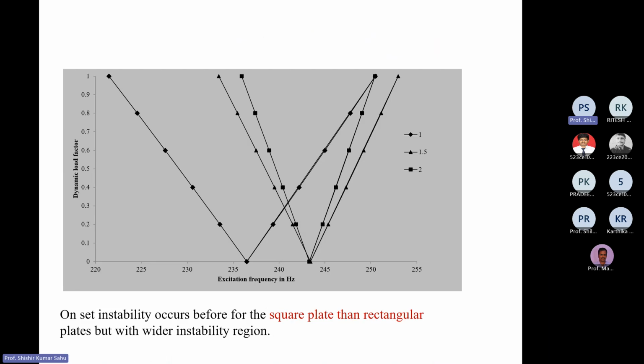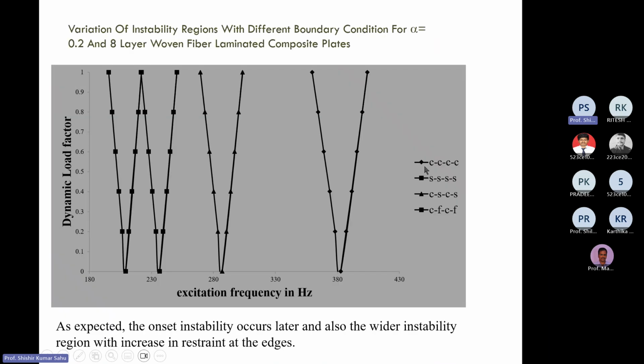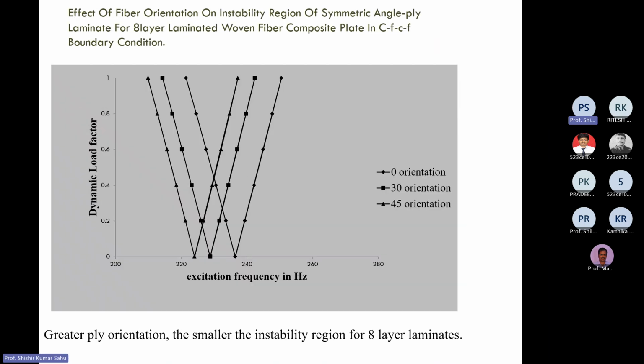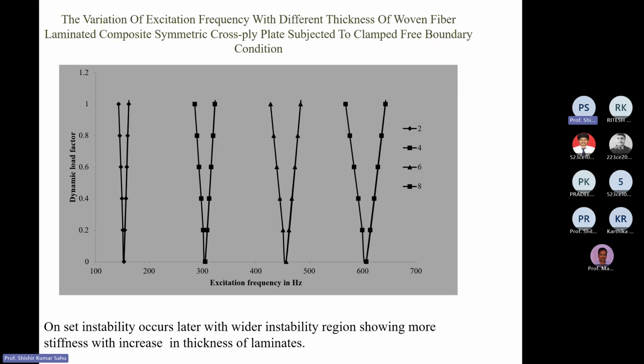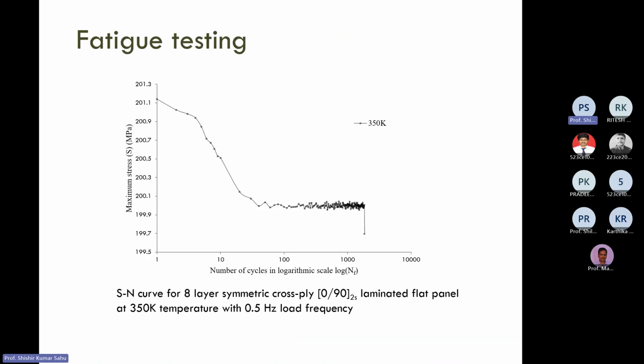The dynamic instability regions have been plotted for square and rectangular plates for different aspect ratios, 1.5 to 2. This is for different boundary conditions. This is for clamped. This is for simply supported. Clamped will have higher excitation frequency than the simply supported one. Then orientation, and again number of layers.